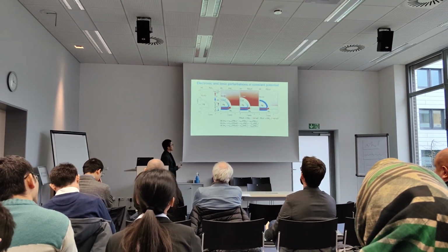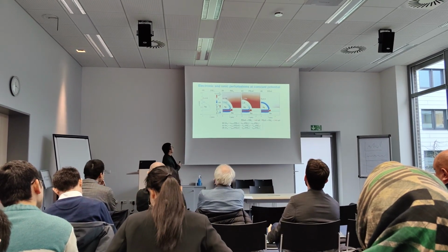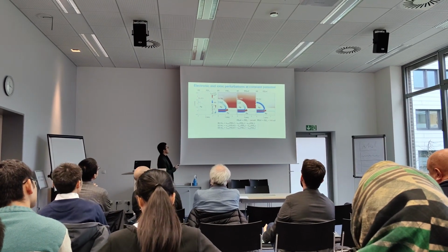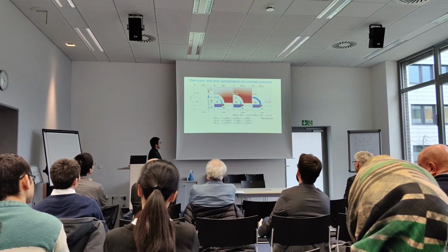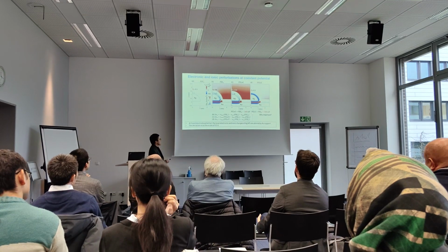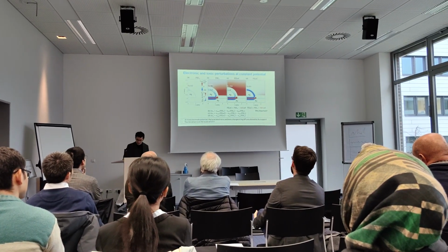What happens if we increase the potential by 340 millivolts? We recover the ionic state. You see, they are the same, but the local electronic state deviates further from the original state. So you see that it exerts a 0.5 volt difference in the local ionic and electronic states. Okay, let's go to the next slide.